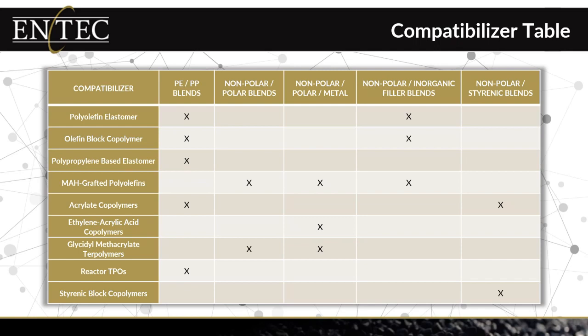And so with multi-layer film scrap, you need to not only compatibilize the polar and non-polar material, but you may also need to compatibilize the metal. So once again, typically what we're going to have here is one of these reactive modifiers like a MAH or GMA modified. One of the things I would comment though is if you have only a non-polar material like polyethylene or polypropylene and metal contamination, I would tell you that the acrylic acid copolymers will probably work as well or better in that particular situation.